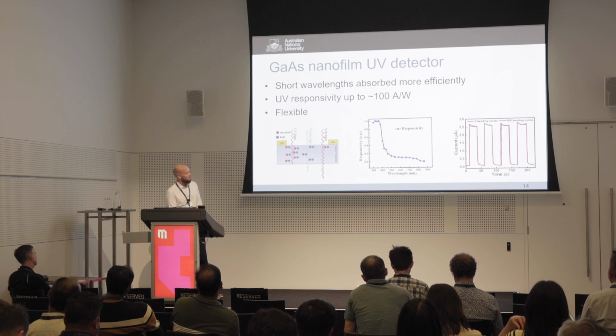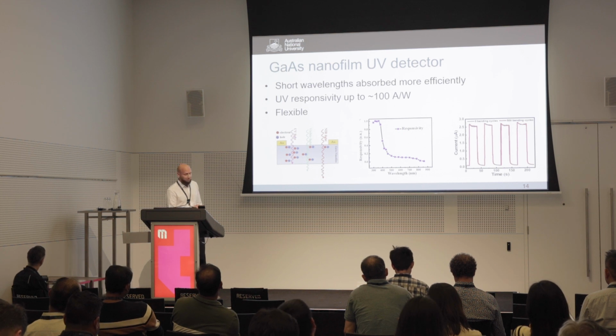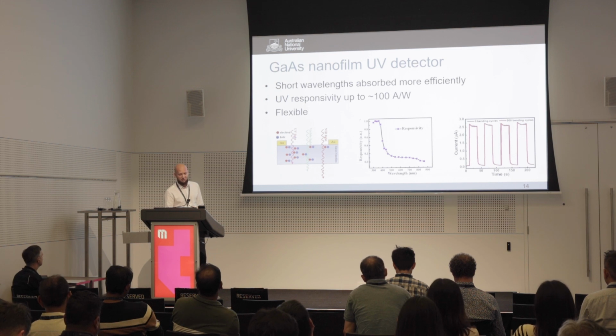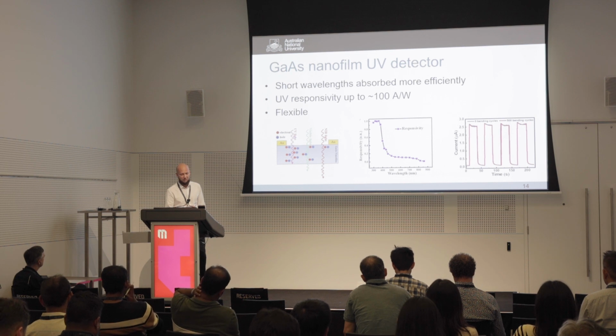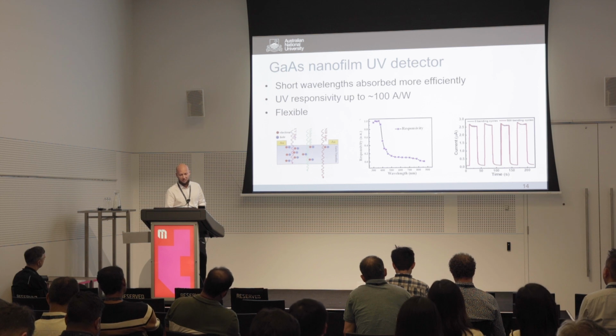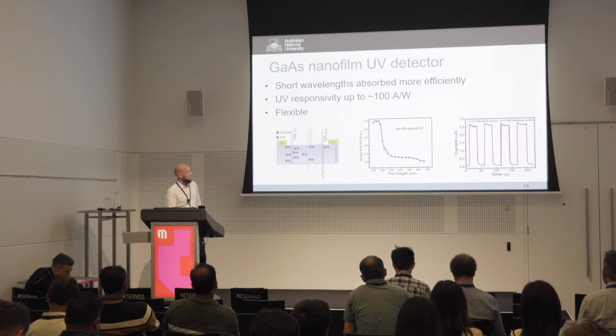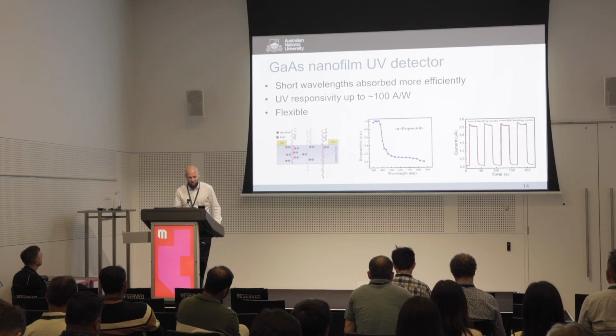That's also seen here in the responsivity curve, which is quite low in visible and infrared, and about 10 times higher in the UV region. And again, although this was a very simple device, the responsivity was up to about 100 amperes per watt, which is on par with similar MSM devices made out of thick wide bandgap semiconductors. And the flexibility is shown here. So before and after 500 bending cycles, there's pretty much no change in the behavior of the sensor or detector.